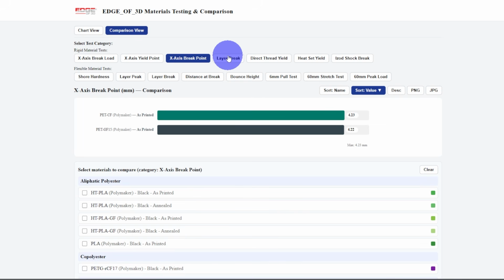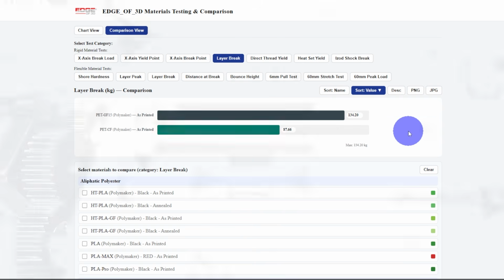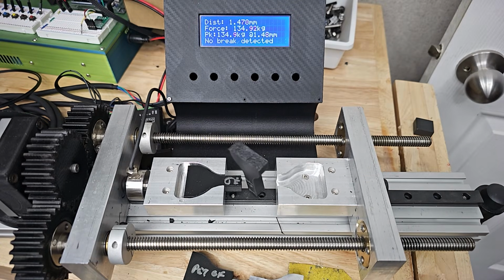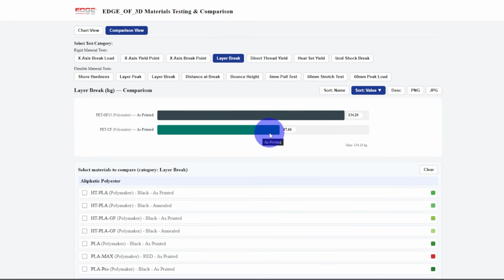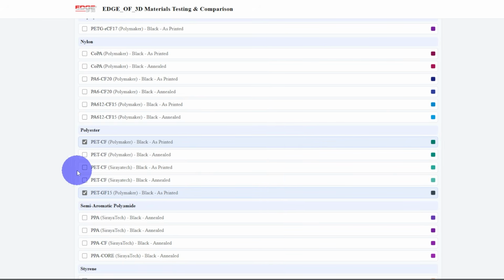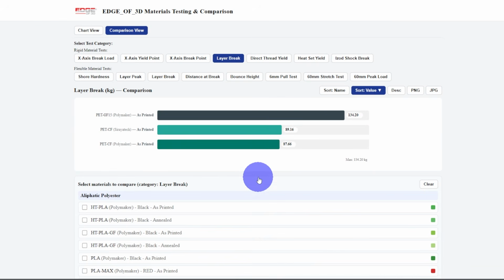Now, here's where things start to get impressive with this material. Layer adhesion. One of the complaints on the PET carbon fiber is delamination and layer adhesion. And as you can see right here, 87.66 kilograms of force on the carbon fiber, 134.2 kilograms of force on the PET glass fiber 15. Let's go ahead and pop a SunyaTech unannealed in here. And you can see that it beat the SunyaTech as well. The SunyaTech carbon fiber is about the same as the Polymaker carbon fiber.